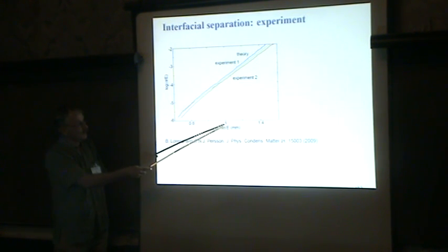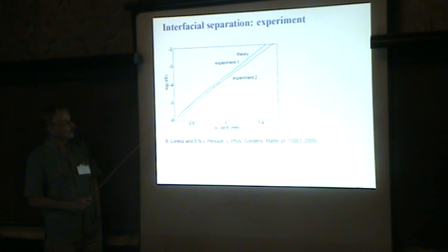We're measuring separately the elastic modulus, and we're measuring the power spectrum. We obtain this fit without any fitting parameter. There's only some deviation at very low applied pressures. In fact, this experimental curve will start to go down here. And that's because the experiment is for a finite system, while the theory is for an infinite system.